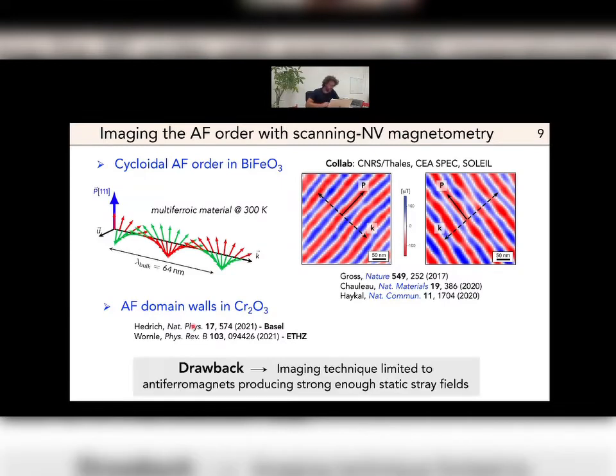Still, there is a drawback here: intrinsically, the NV magnetometry technique is restricted to samples that produce a strong enough magnetic field. So if you consider a perfectly compensated antiferromagnet, then you won't be able to image its structure because it will produce no stray field.